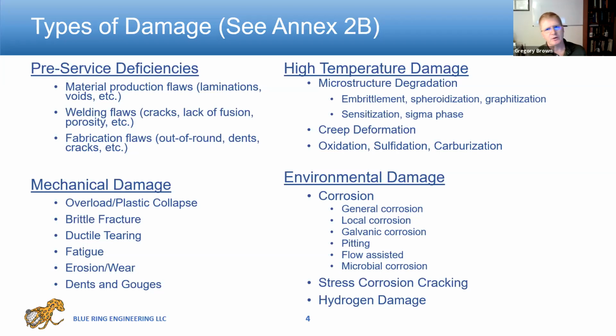So when we talk about damage, what type of damage do we have? Well, we can have what are called pre-service deficiencies. What are these? Fabrication defects. Maybe our welding was not done properly and we ended up with cracks in the weld, or porosity, or bad material properties. These are things that happen in fabrication. Hopefully we can find these with inspection before we put the equipment in service. You can get damage due to mechanical operation. A good example is fatigue damage. We have cycles on equipment. So imagine pressure oscillating. This can eventually initiate a crack. That crack could then grow and cause failure of that equipment.